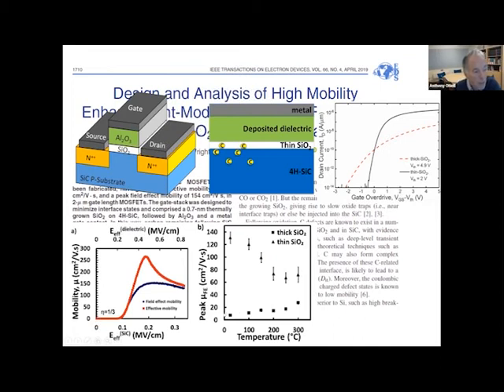Down here with the thick oxide, we've got Coulombic scattering because you're getting scattering off the carbon defects. And as the temperature increases, your electrons are spending less time in the vicinity of a carbon defect, so the mobility goes up in a hand wavy sort of way. What we're finding up here with our thin oxide data is that we're getting a reduction, a negative temperature gradient corresponding to phonon scattering because we got rid of the Coulomb scattering. And if you think of phonon scattering, then you can imagine as the temperature goes up, you're getting more lattice vibration and therefore more mobility degradation as a result of that.